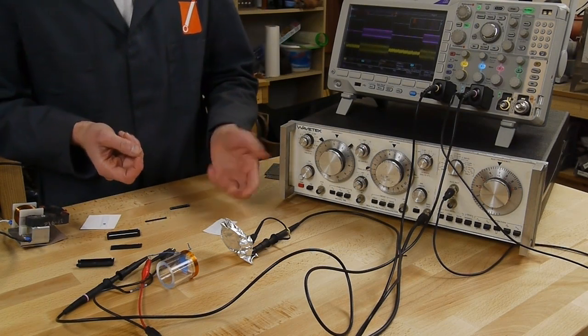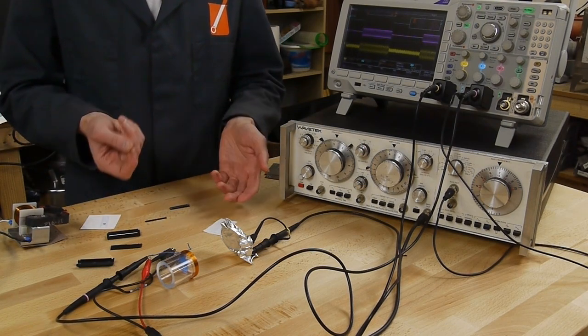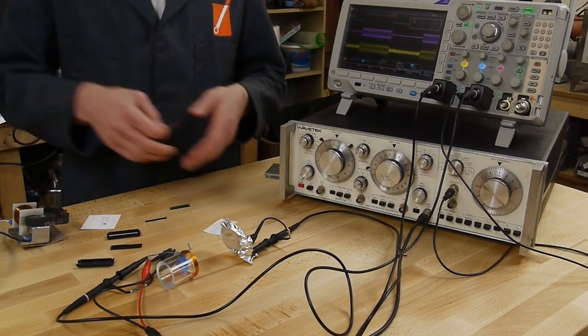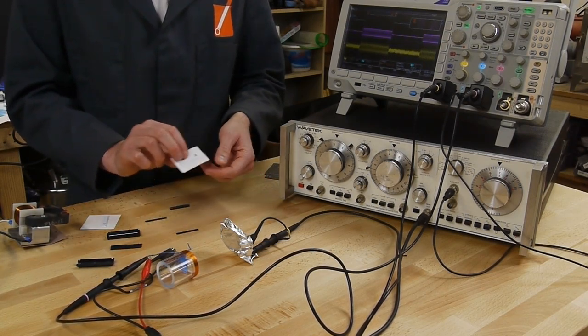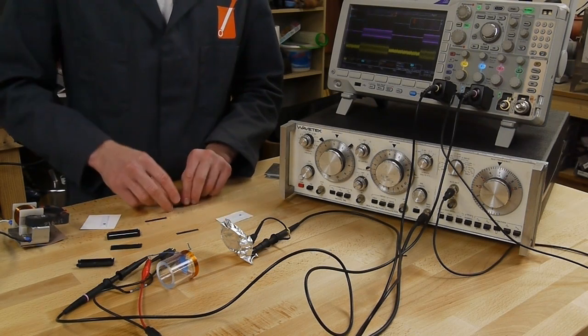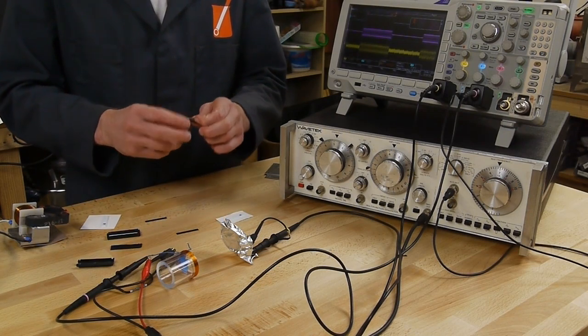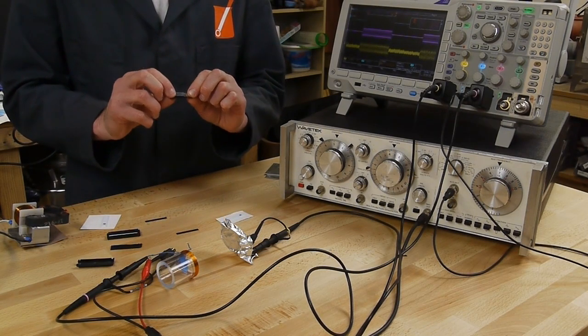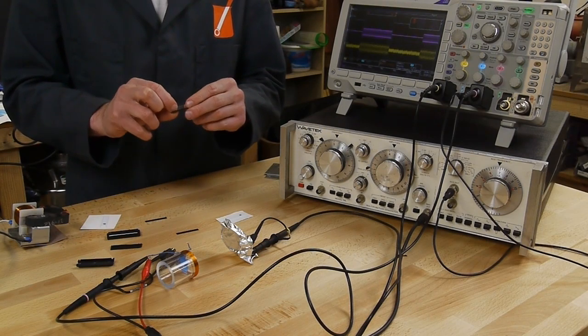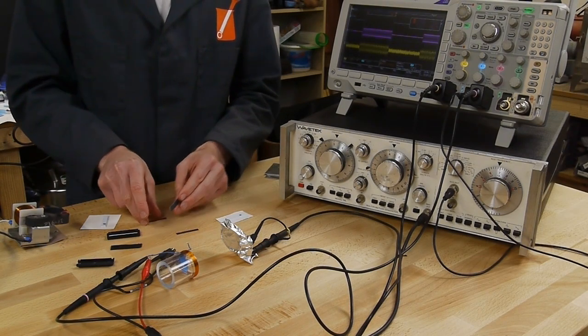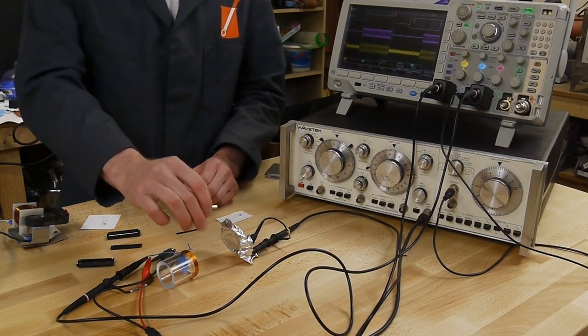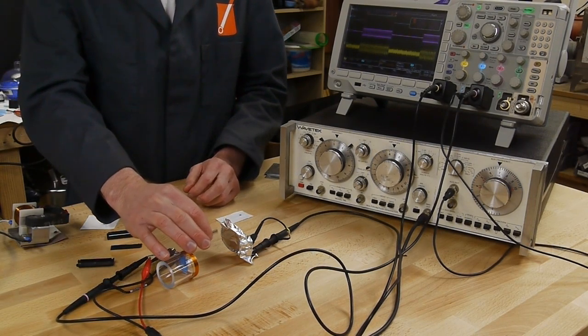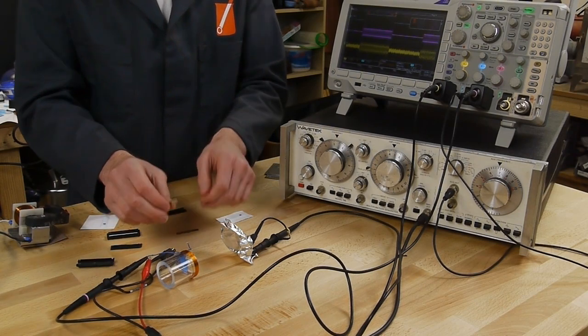You might be wondering how you actually turn them on and off. The next trick: if we had this tag that oscillated and you go through the doors and it goes off, that works, but how do we turn the tag on and off? The other trick is this other bit of metal in the tag is actually a magnet, a very small weak magnet. One of the tricks with this oscillating strip of metal is that in no field, like in Earth's magnetic field, and then we're transmitting this 58 kilohertz AC magnetic field onto it, it doesn't actually want to oscillate all that much.